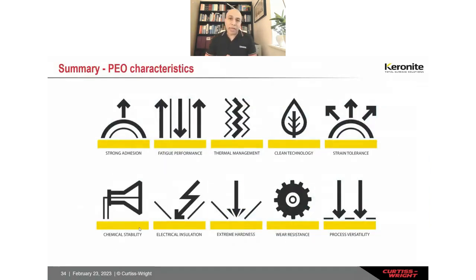To summarize, PEO characteristics: it has got strong adhesion because it is a conversion technique rather than a deposition technique. It has got very good fatigue performance, much less fatigue debit than hard anodizing. It's a clean technology, highly strain tolerant, and importantly, it is an inert ceramic and hence chemically very stable. It gives very high electrical insulation because it's an aluminum oxide ceramic, in the case of aluminium. Extreme hardness because it's a corundum you can create on aluminium, and subsequently extreme wear resistance.